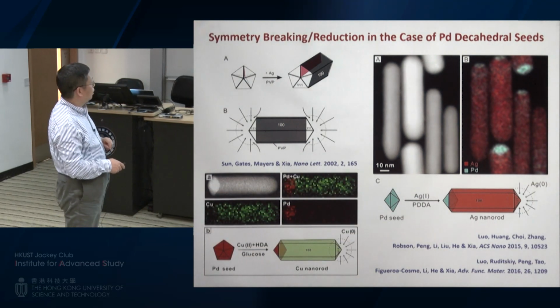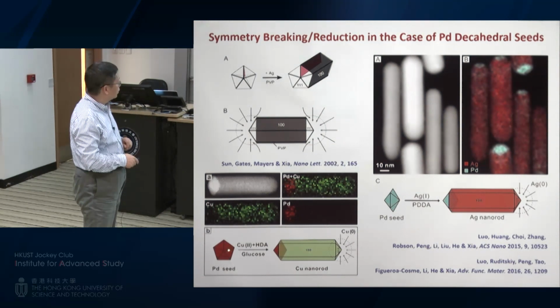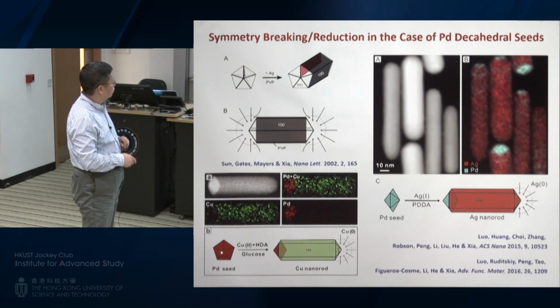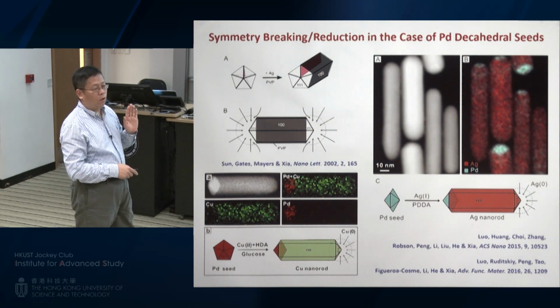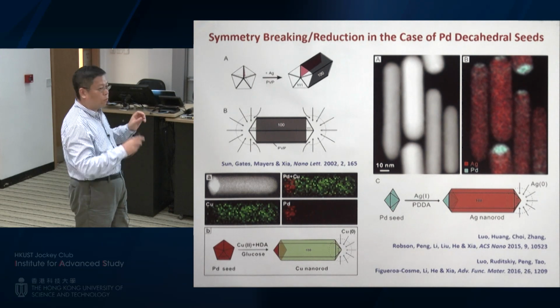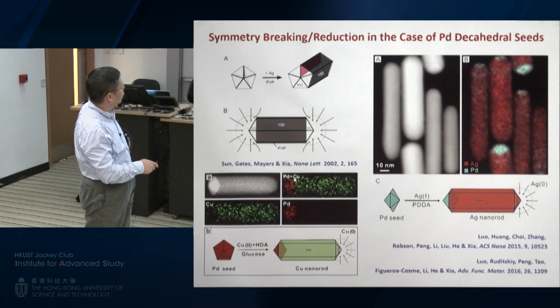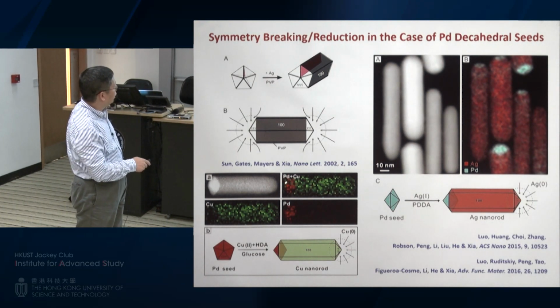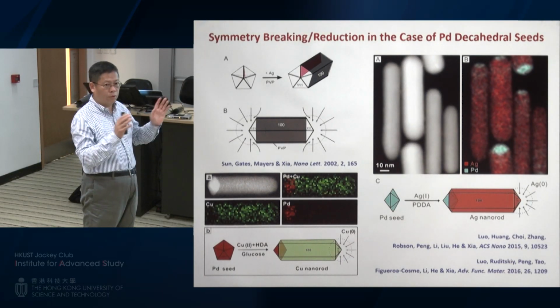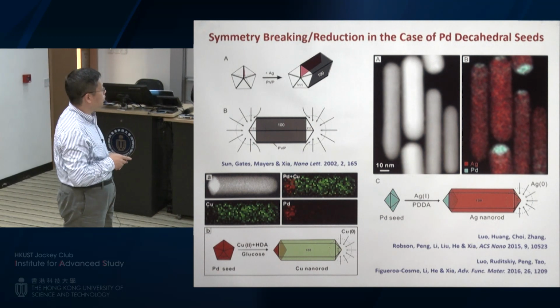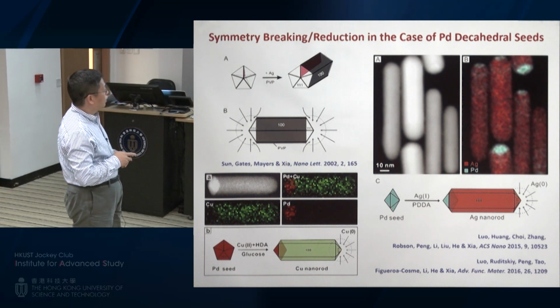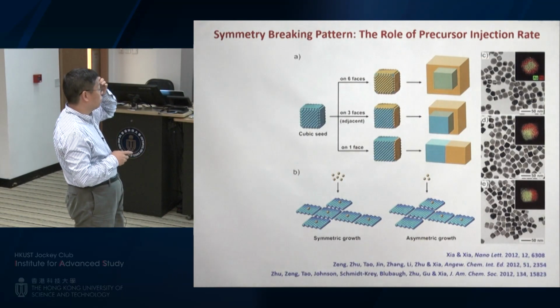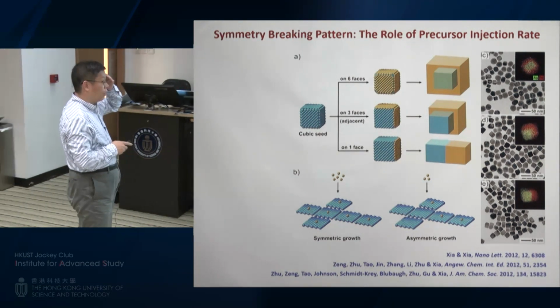And here's something we published last year. This is for copper. It's a similar system. It's a palladium decahedral seed. You have copper being deposited. Again, it's only going to be along one side of this seed, not both sides. So that's why finally this palladium will be located at one of the ends. It's not in the middle. Okay, the symmetry is broken during the growth process. So why is that? Then we started to do some other demonstrations to figure it out.